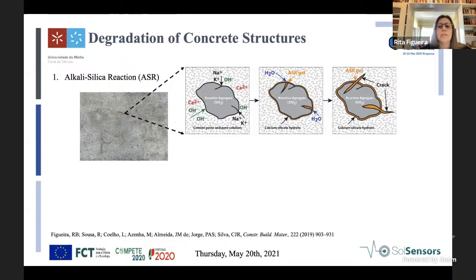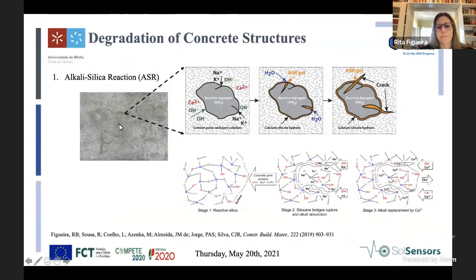When you have moisture, that gel will expand, and after expanding, it will lead to the formation of cracks like this. You can see in this picture. In this figure, you can see these 3 stages of alkali-silica reaction taking place. After the gel expands, the crack occurs.